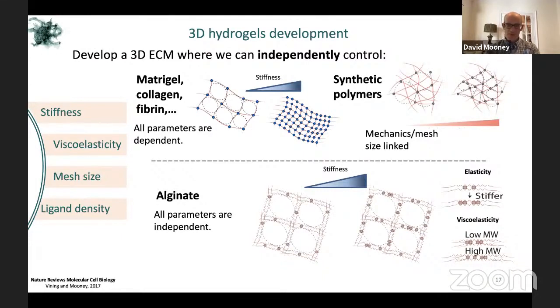And so when it's an alginate gel, if one cross-links it to a low level to make a relatively soft gel, as indicated by these few red dots, basically bridging adjacent polymer strands where we have these G-block structures, all the polymer chains end up falling into a specific alignment. And then as we add more and more cross-links, we in essence just occupy more and more of these locations that are already aligned adjacent to each other. So we can make the material more stiff without changing the nanoscale architecture. So we don't change the mesh size or diffusional transport. Further, we can independently vary the viscoelasticity versus the stiffness by controlling the molecular weight of the polymer chains, which allows us to alter their relative mobility and thus their ability to dissipate stresses independent of stiffness and these other variables.